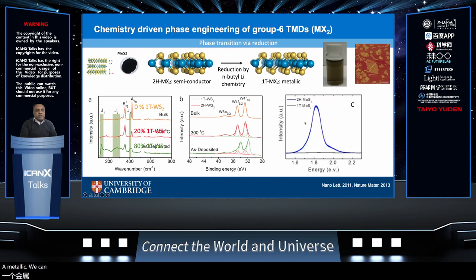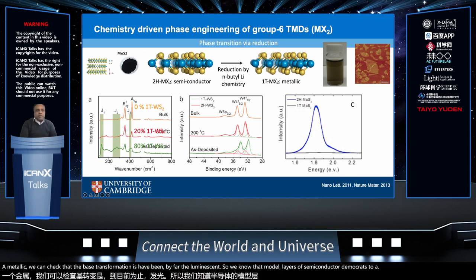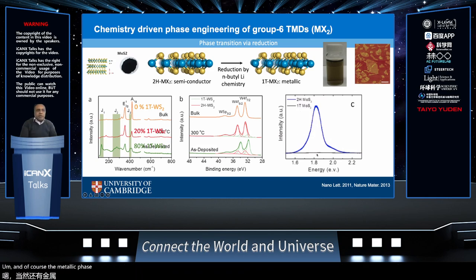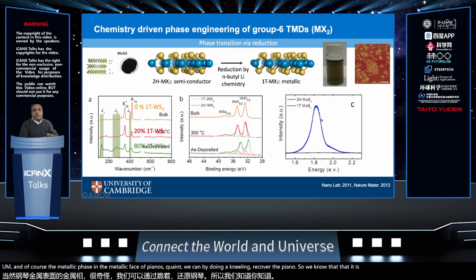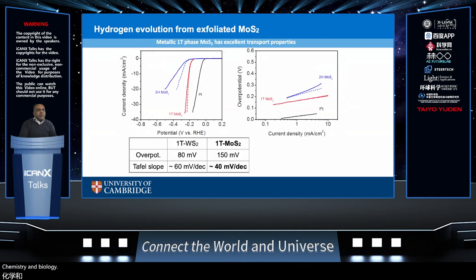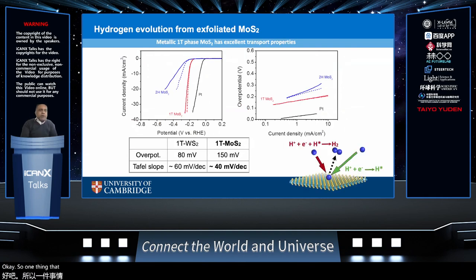We can check that the phase transformation has happened by photoluminescence. So we know that monolayers of semiconducting MoS2 have this characteristic PL. And of course, in the metallic phase, the PL is quenched. By annealing, we can recover the PL. So we know that it is actually the phase of the material that's changing and not some chemistry in the material.